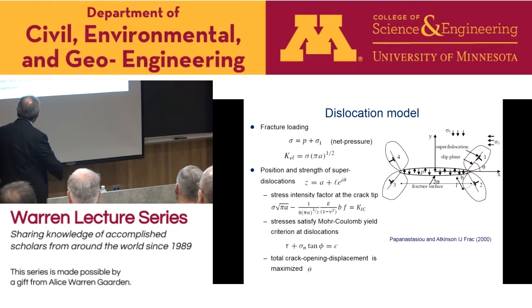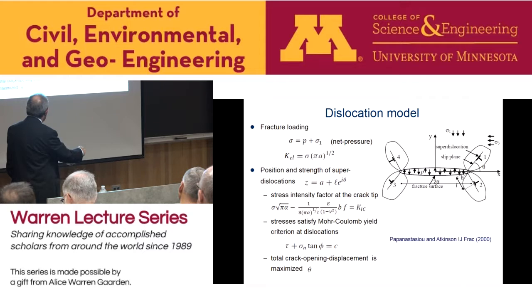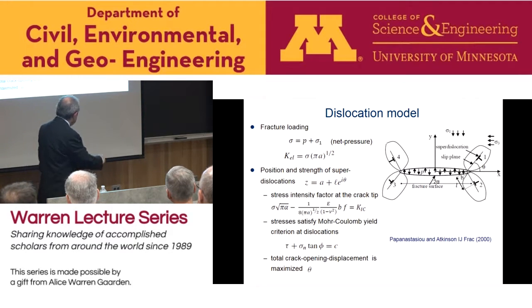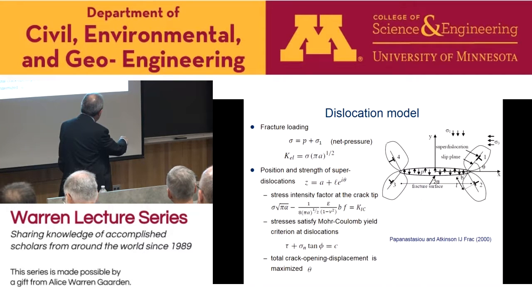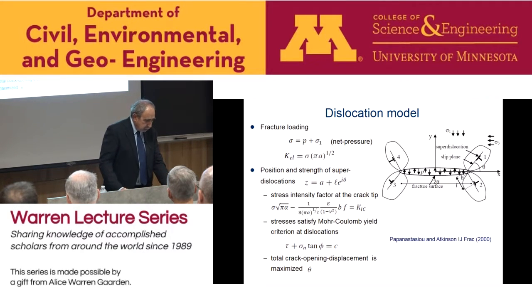And the condition we use is that the stress intensity factor at the fracture tip, due to the loading and due to the contribution from the dislocation, should be equal to the fracture toughness of the rock. The stresses at the superdislocation should satisfy Mohr-Coulomb, the yield criterion, and also the crack will act in such a way as to maximize the crack opening displacement. And this condition gives us theta, the inclination of the superdislocation.